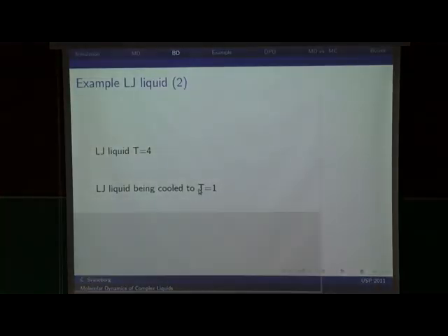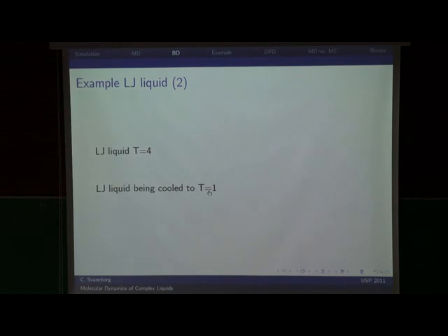But now we could ask what happens if we wanted instead to decrease the temperature. Now we're just going to increase the speed of the simulation a bit. And what you cannot see, but what will be apparent, is that these particles are not moving as fast as they did before. Essentially what has happened is that they crystallized into a hexagonal order. And this is just by taking the previous simulation and saying, I do not want to simulate at temperature 4, I want to simulate at temperature 1. Then it extracts heat from the system, and the system crystallizes as we expect. Very simple.